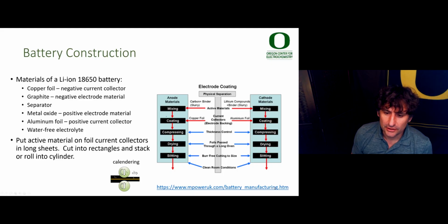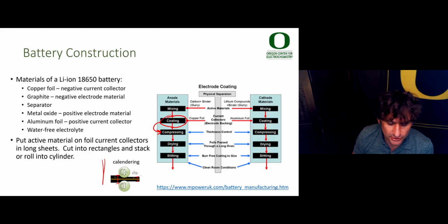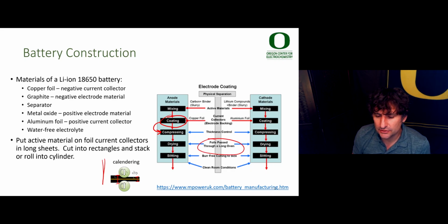We take these coated foils and they get compressed, usually by a process called calendaring, where they're fed between two rollers to go from the initial thickness to a compressed thickness. This has a big effect on the microstructure, the porosity of the electrode. So this is a process that needs to be very highly controlled. You pass those foils through a long oven to remove solvent that's used to prepare the slurry and the ink.